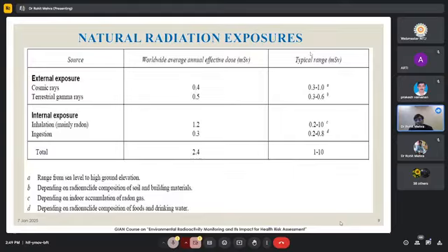Though deeper studies are required to reach final conclusions, if radium, thorium, potassium activities are increasing, that depends upon the quality of the coal also. Because it's not the case that for every similar admixture in the ratio, say 10% of fly ash and 90% OPC, 20% of fly ash and 80% of OPC, 30% of fly ash and 70% of OPC, will give the same results. It is not there.